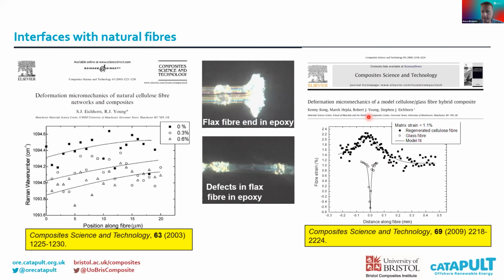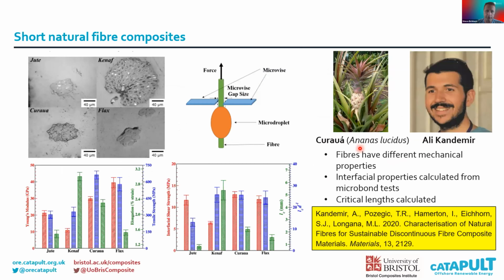And we used a little dopant inside the glass fibres, so we were able to make some glass fibres using samarium fluoride and samarium oxide, which are luminescent, and then map across the defects in the composite structure. But on to some more recent work, and Ali Kandemir, pictured here, is the brains behind this. We've been looking at a whole range of different natural fibres with a view to using short and discontinuous fibres in recycled composites, or composites that could easily be made into flexible parts and so on.